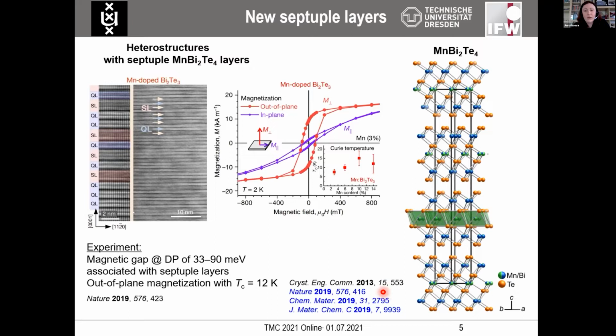So in 2013, there was a first paper reporting that probably a bulk compound with stoichiometric ratios of manganese and bismuth can exist, and that this compound may be built out of the septuple layers, exactly the same ones that were observed in this heterostructure. The problem back then was, as reported by the authors of this paper, that the compound seems not to be very stable. All attempts to quench it from the higher temperatures and to get a crystal or somehow characterize its physical properties have failed because it seemed to decompose as the temperature is decreasing.